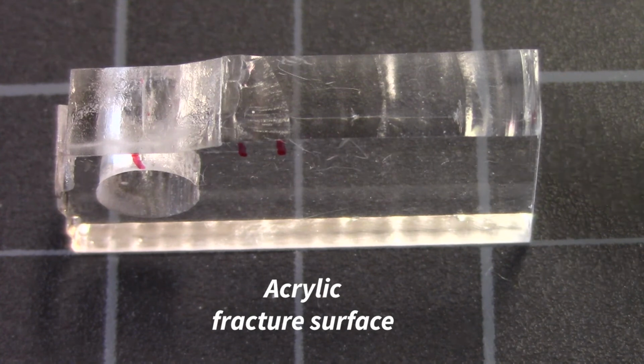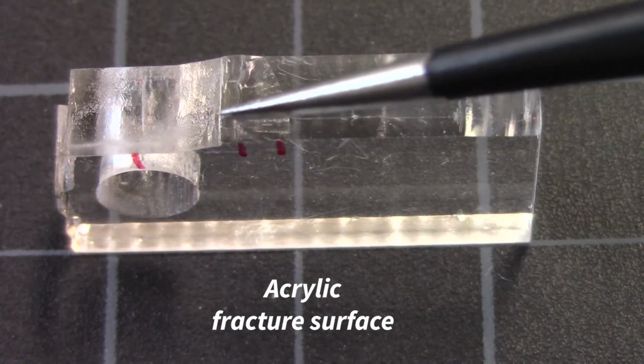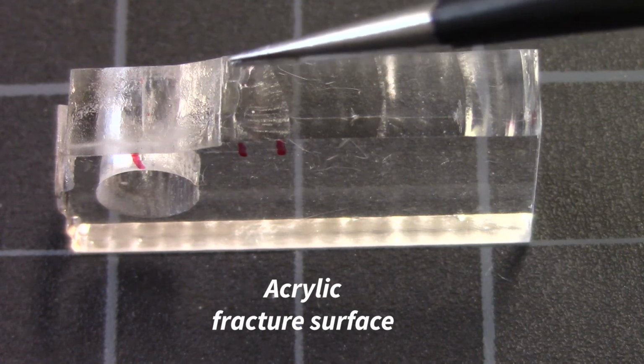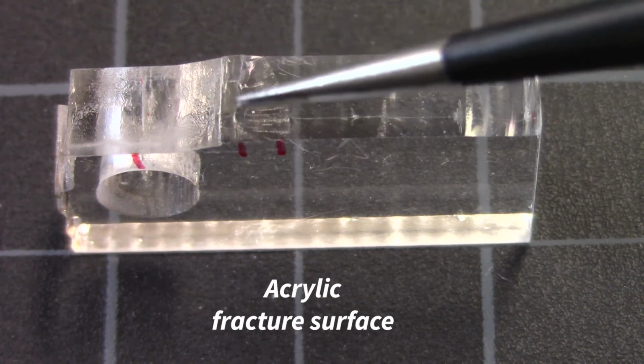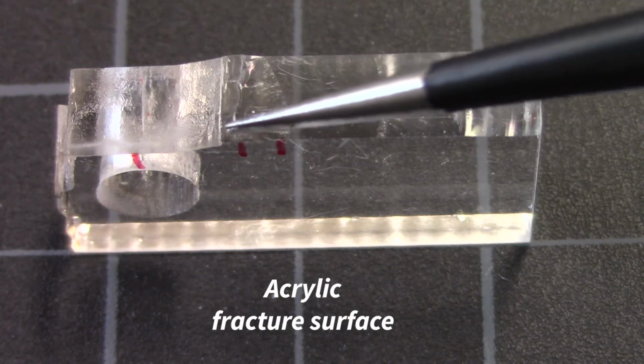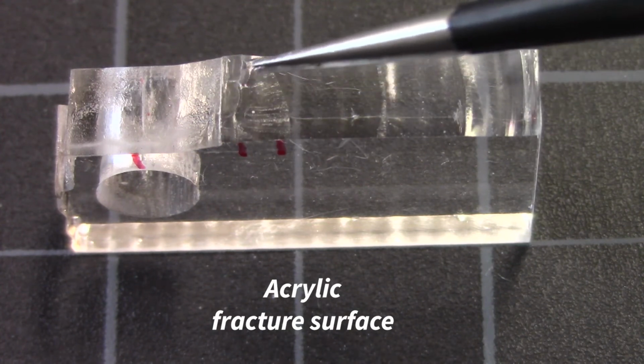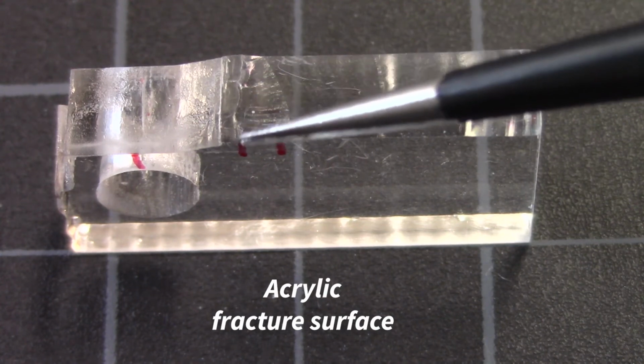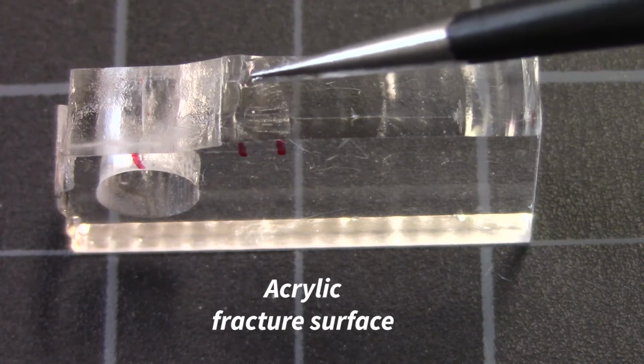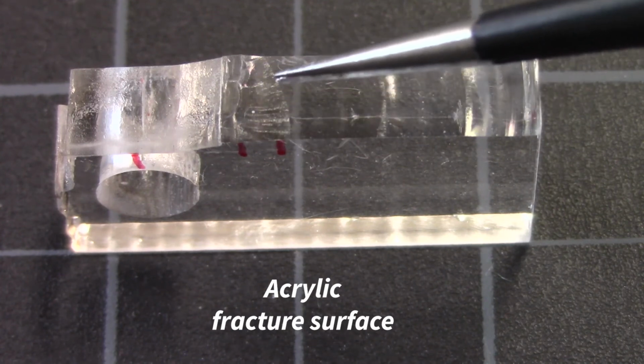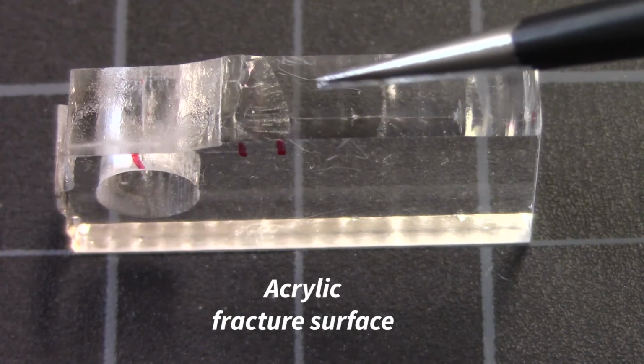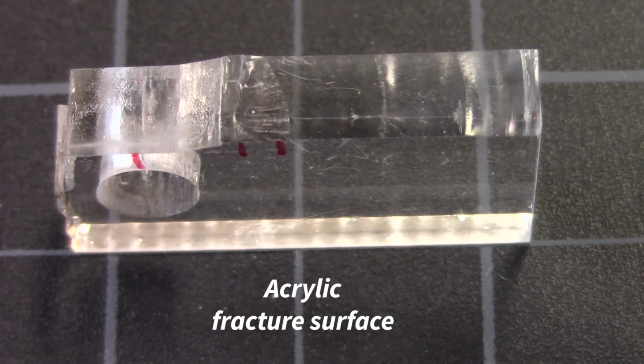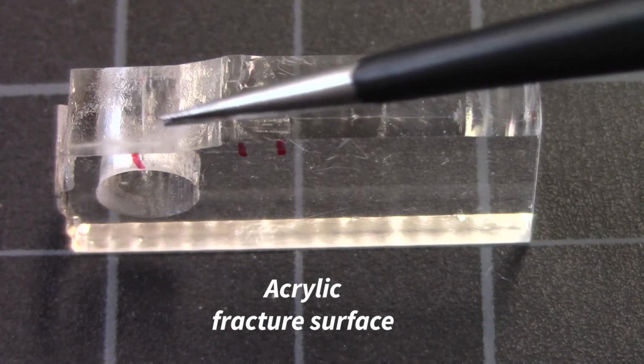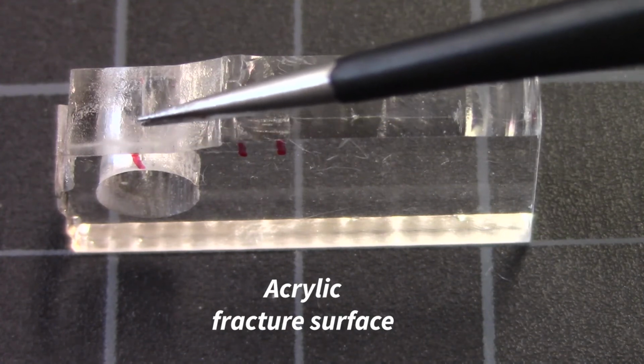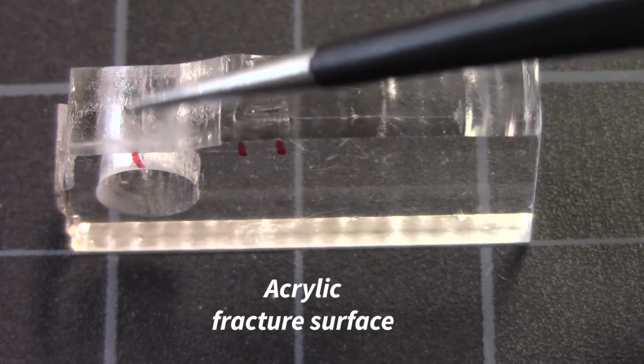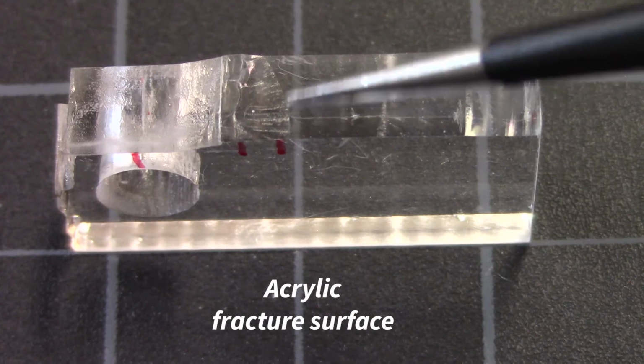There's a close-up of the acrylic specimen after fracture. We have the leading edge of our starter notch here, then a smooth, shiny surface up to this first red line. That's our pre-cracked surface, and then a slightly more striated shiny surface between these two red marks. That's our crack propagation region. And then after this crack propagation region, we have our fracture surface. So the final A dimension, the crack length, will be measured from the center line of this loading hole to the leading edge of the crack prior to fracture.